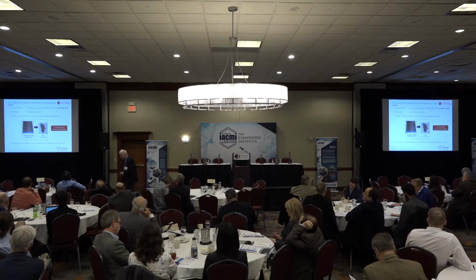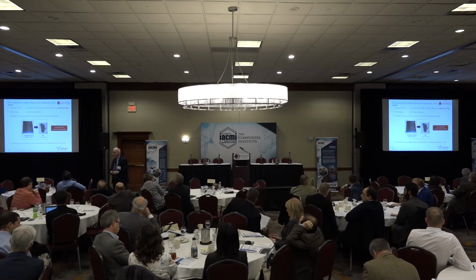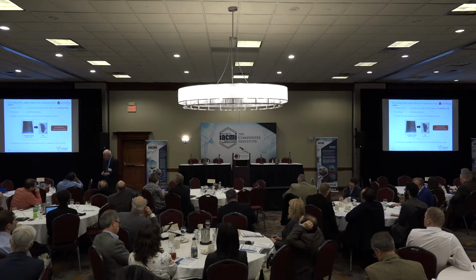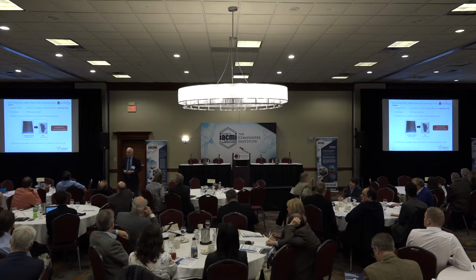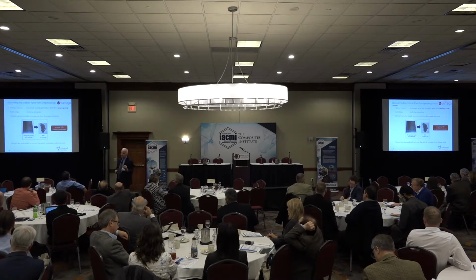And here's some work on recycling that we've done in conjunction with Vartega, and I think Andrew Maxey's in the audience there. Vartega's focus is really on recovery and recycling of carbon fibers from prepreg scrap, and their technology involves a multi-step extraction process. What we did was to send some of the Renegade Prepreg to Vartega to run in their process. And they found that they could easily remove the resin. They took this prepreg from about 35% resin down to 1 to 2% resin without any optimization, showing that the vinyl ester resin is readily removed from the prepreg scrap, much easier than it can be done with epoxies.